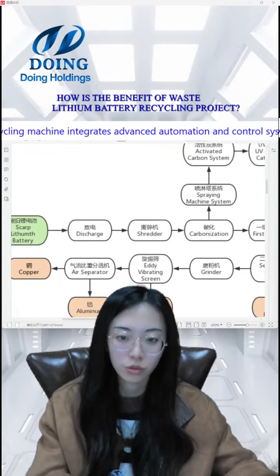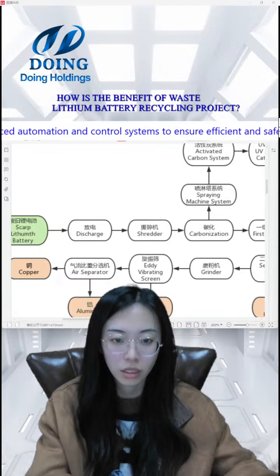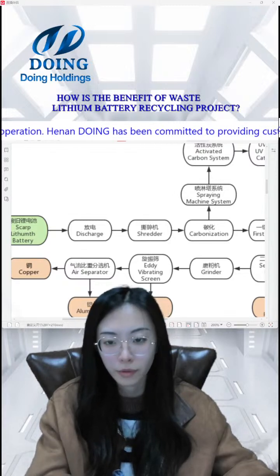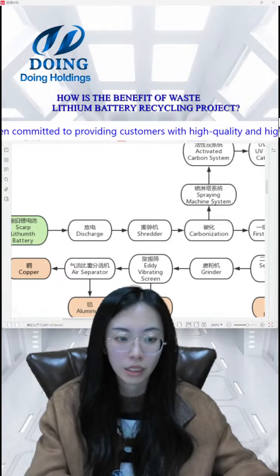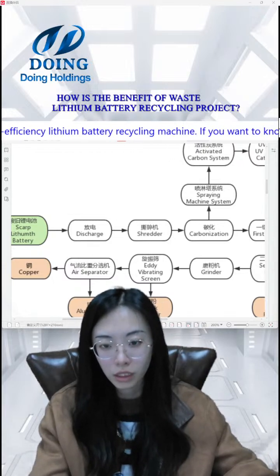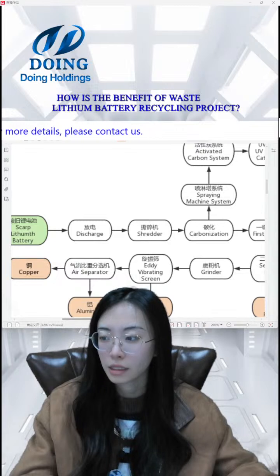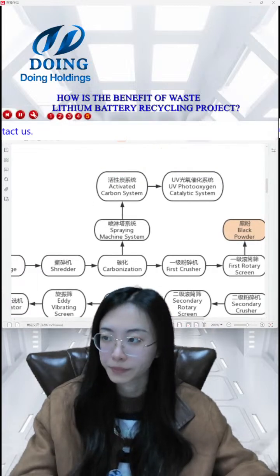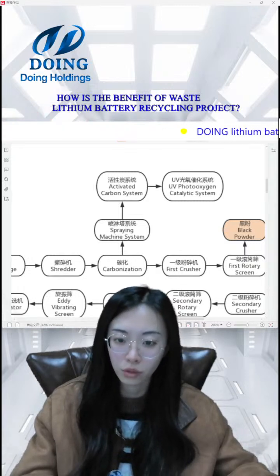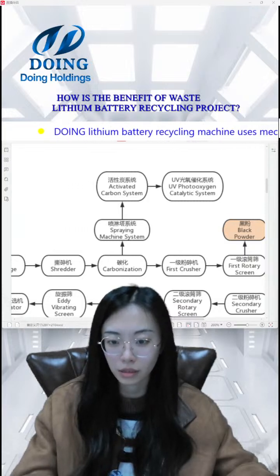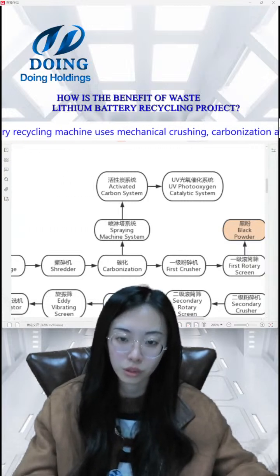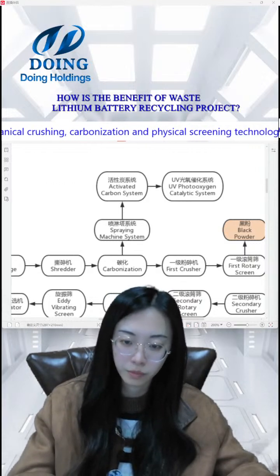We dry them at maybe 100 to 400 degrees, and all the water will evaporate, and the electrolyte also evaporates. Then we can put it into safe treatment. Because the carbonization furnace has a heating system, there will be some dust and smoke, so we need a purification system to purify them. We have a high-level purification device and a normal level, depending on your region and environmental policies.